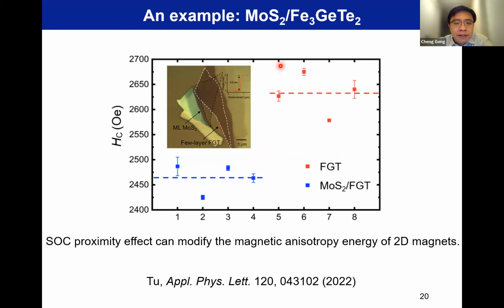So here you can see there is a few-layer FGT, around 8 to 10 layers. I remember it's 8 nanometers, so it's not so 2D. But when we put one monolayer molybdenum disulfide to cover part of this 8 nanometer FGT, you can still see in these two regions, at a certain temperature, when we measure the hysteresis loop. We sample several different positions here and different positions here. You do the hysteresis loop, you can get the coercivity. You find the one-layer molybdenum disulfide covered region has around 180 Gauss smaller coercive field than the bare FGT.